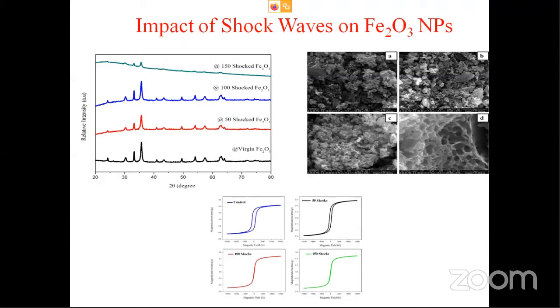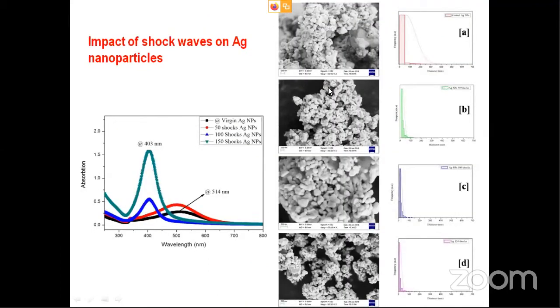So, another interesting thing. See the Ag nanoparticles. Initially, this is the control. This is 50 shocks, 100 shocks, and 150 shocks. You can see the UV spectra. The morphology you can see, the control is the black one. This is the morphology, and the size is around 50 nanometers.